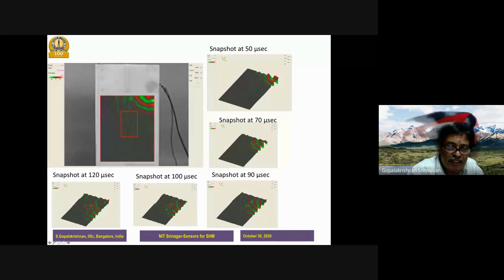When the laser falls here, the wave starts propagating, and I monitor this small region. Initially, the wave comes here. This is at 50 microseconds, 70 microseconds, 90 microseconds, 100 microseconds, and 120 microseconds. And there is the damage here in the square region marked. You see that when it reaches here, it completely changes the wave pattern. Clearly you can see that there is some damage here at the interface. You can locate the damage very easily.